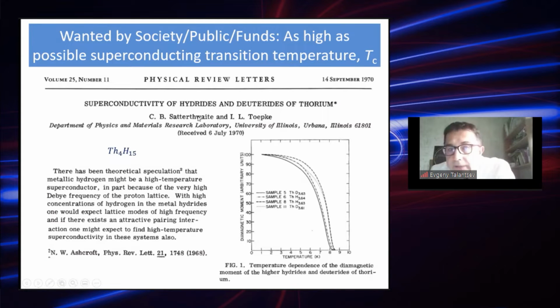Two great guys, unfortunately I can't pronounce the last name of the first author, came to a very clear and very robust idea, which works now: if there is a lot of hydrogen in the compound, it doesn't matter if there is some additional heavy metal there. It should work because of high frequency phonons. Following that idea, they synthesized the first and presumably the last superhydride at ambient pressure, which is thorium 4H15. What was most puzzling is that they did not observe the isotope effect. Actually, they observed the absence of it.